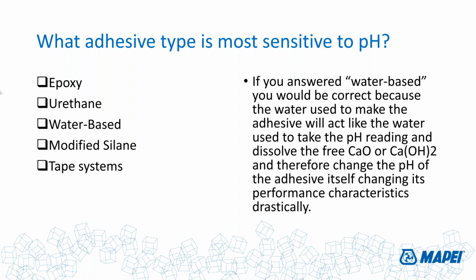So if you ever wanted to know why we tell you not to install on concrete slabs with water-based adhesives at pHs that are higher than 11 or 12, this is the reason. Because the higher you get, and this is a logarithmic scale, a pH of 8 is 10 times higher than 7, and the next is 10 times higher again. So it's a very high concentration of hydroxyl ions when you get into that pH of 12, 13 to 14. It's the kind of stuff that will burn your skin. This is nothing to mess with.